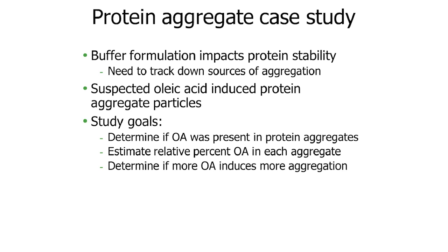The user here suspected oleic acid was inducing aggregation of their protein and wanted to find out if that really was the case. So with this in mind, the user wanted to determine if oleic acid was present in their protein aggregates, and if so, they wanted to estimate the relative percent of oleic acid present in each aggregate. This information could then be used to determine if more oleic acid leads to more protein aggregation.